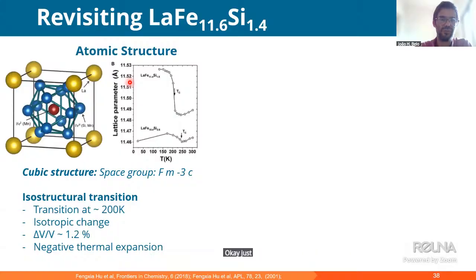Okay, just to revisit, this material has a cubic atomic structure with this space group. It undergoes, as I told you, an isostructural phase transition, meaning it retains the space group, but it contracts a lot at the Curie temperature, about 1 to 1.5%. In its present form, the transition is at 200 K. However, via hydrogenation or other chemical substitution, we can shift this temperature up to room temperature. Isostructurally, this means it's an isotropic change in the lattice, and it has a negative thermal expansion.